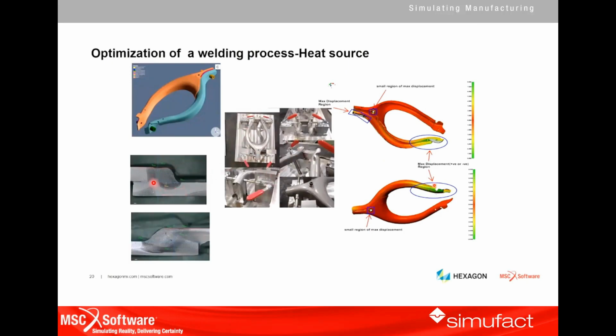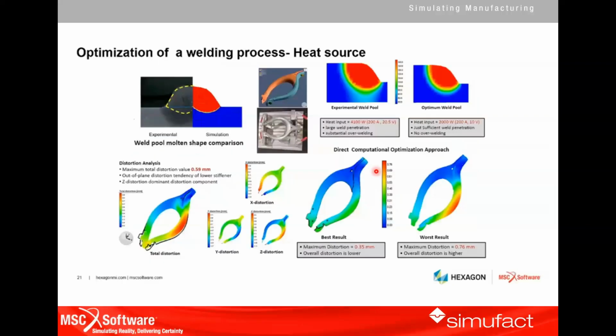And here we can see the weld macrograph after the welding is done. When we see the macrograph, we can see the heat penetration and the fusion zone, and all these parameters can be seen. After doing the simulations, we can see some distortions in the component at a particular location, which are more than the accepted range. So here they did a study where they wanted to optimize the welding process, mainly the heat source. From the experimental weld pool, you can see the weld pool distribution here, and the heat input was around 4,200 watts, and they were able to find some large weld penetration happening during the process.